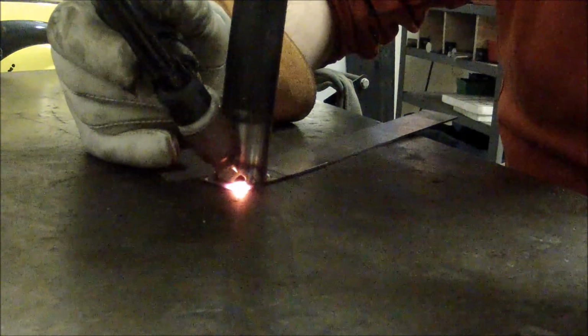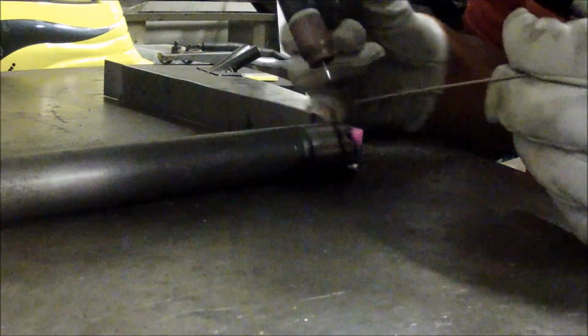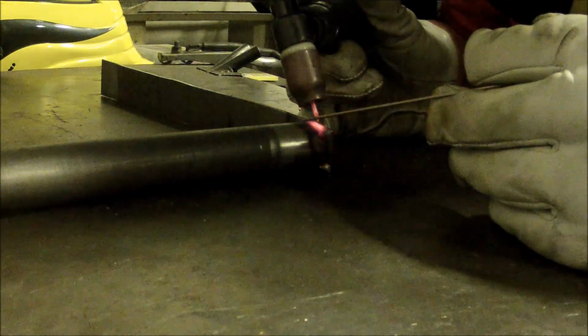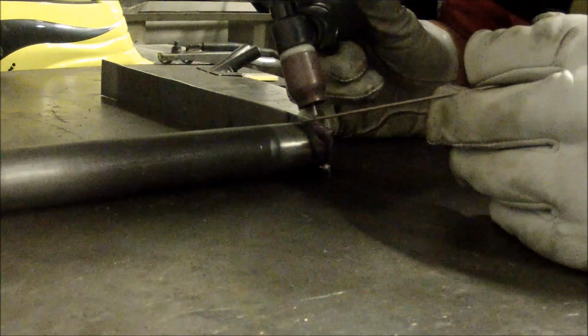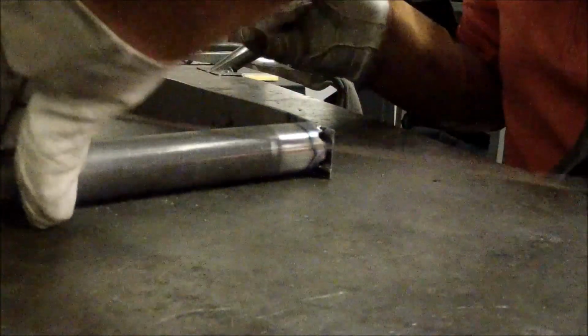Additional tack welds should be placed at 90-degree angles around the pipe. The tack welds can then slowly be connected together. It is important to swap sides of the pipe in order to keep the heat consistent around the pipe, as a part with significantly greater heat will contract, and this will cause the weld to become crooked, or it can even crack.